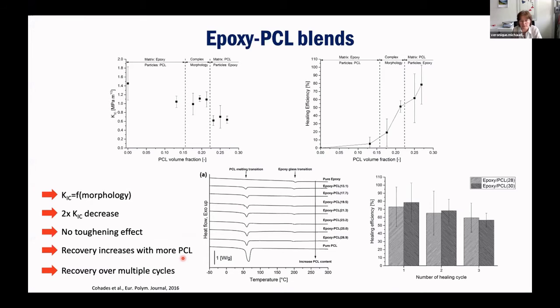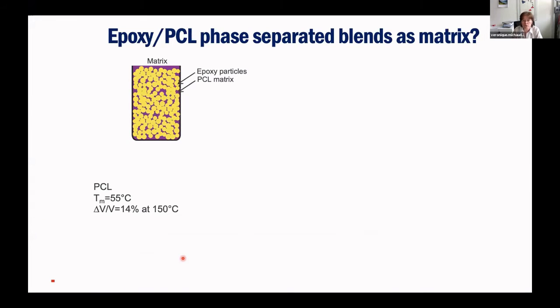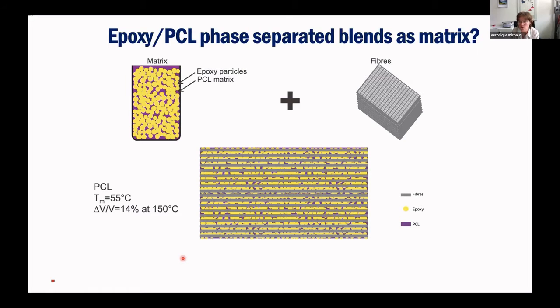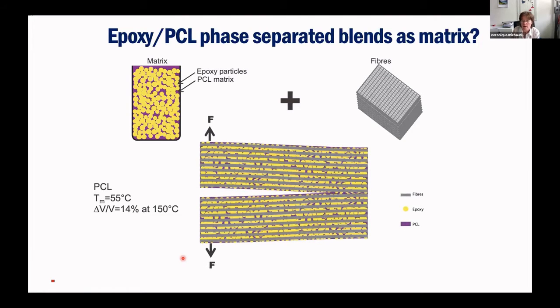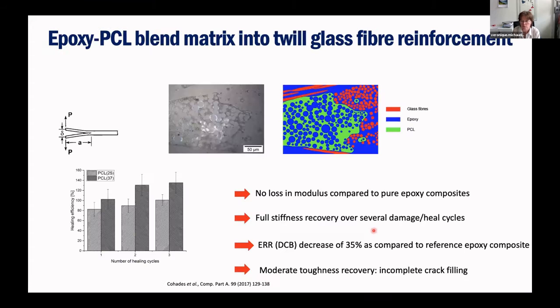We said, okay, let's try this in composites. So we use this as a matrix with fibers, and our goal was always to use structural composites. So at least 50–55% of fibers, a real composite, I would say, not a fake composite with very little fibers. And the idea was to see, if we have a crack, we can open it, we did a lot of DCB tests. And then if you heat, you will close the crack again, maybe not fully, maybe you still have some locations that are not fully closed. We will see that later, but hopefully it should work.